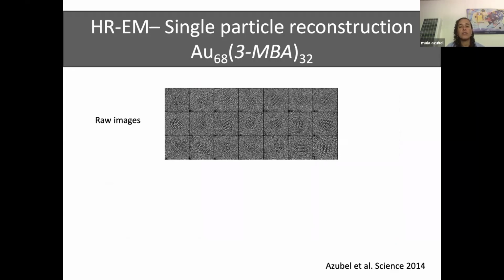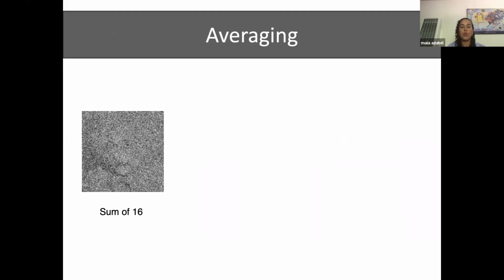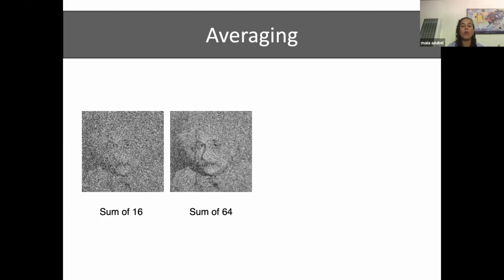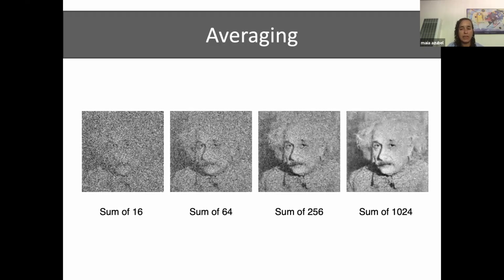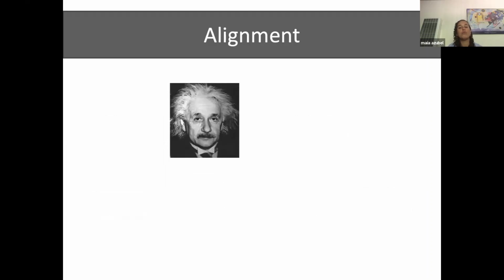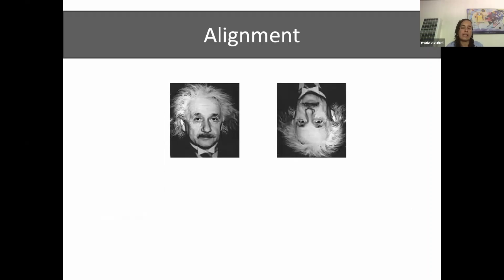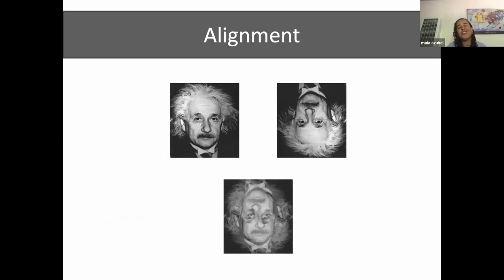And why is that you do averaging? The reason why you do averaging is because your noise is random. So if you have a very noisy image, sometimes you don't see the details. But the moment that you start adding more and more, the picture becomes clear. And that's the reason why you do averaging, in order to improve your signal to noise ratio. However, in order to do averaging that works, the alignment has to be good. Because if you have 2 particles that are exactly the same, not that noisy in that case, but you are going to average those 2, you're not going to get more information, you're going to get wrong information.